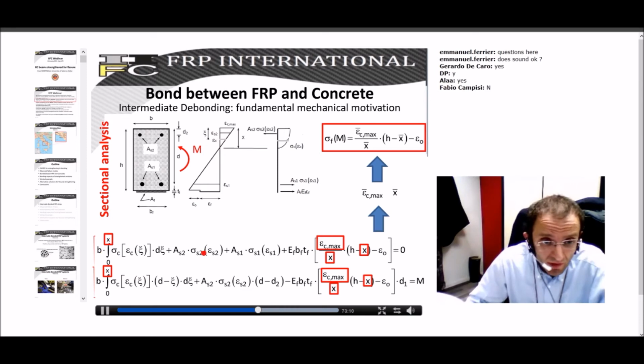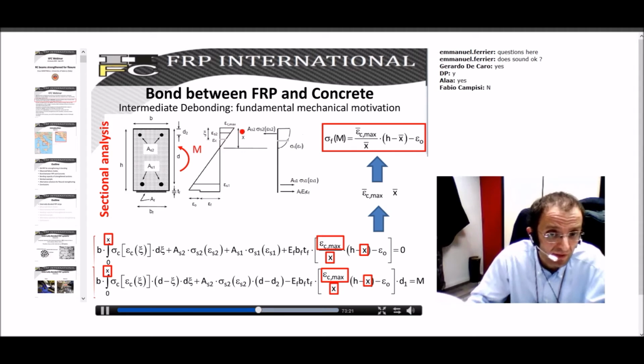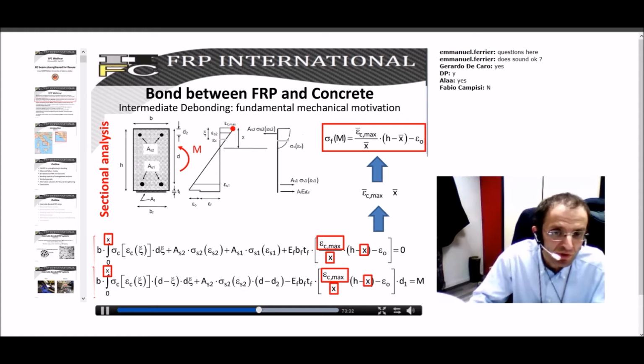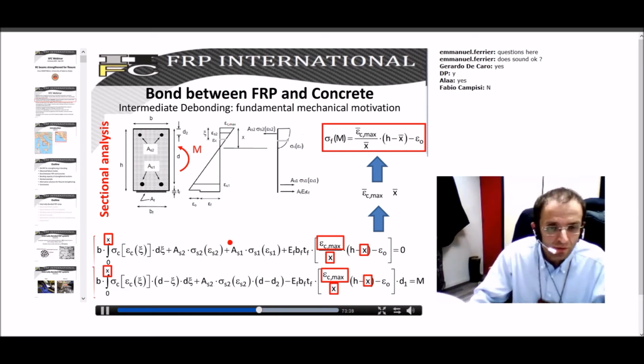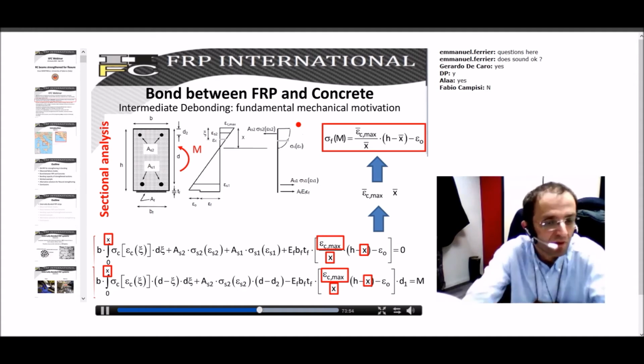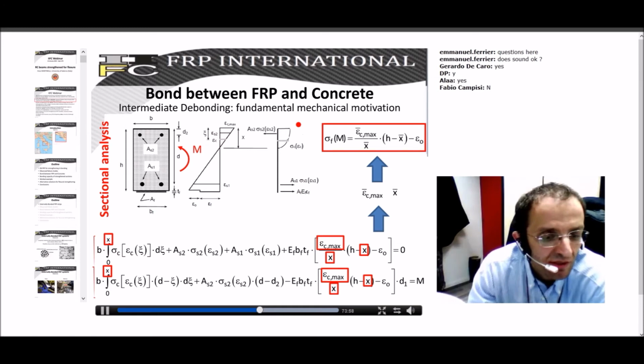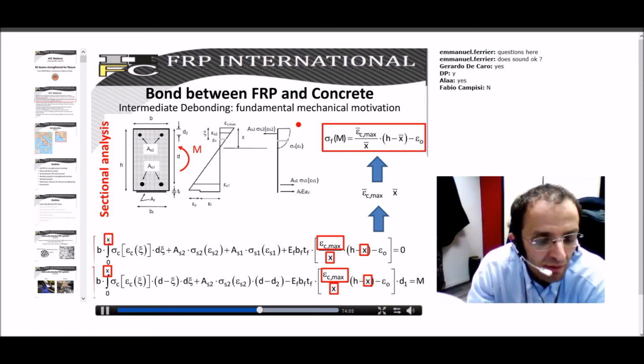This is the equation of equilibrium of forces in the direction of the axis. This is the equation of equilibrium in terms of moments around the neutral axis. So the neutral axis is at the position x from the top chord, and these equations are based on two main unknowns: the maximum epsilon, which controls all deformations, and the position x, which also controls the deformation. So you have two equations in two unknowns. You can solve them depending on the total external moment. You can evaluate how much epsilon maximum is, and then you can evaluate epsilon f, and from epsilon f you can evaluate sigma f. So this is the more rigorous and the most straightforward way to evaluate sigma f in a certain section.